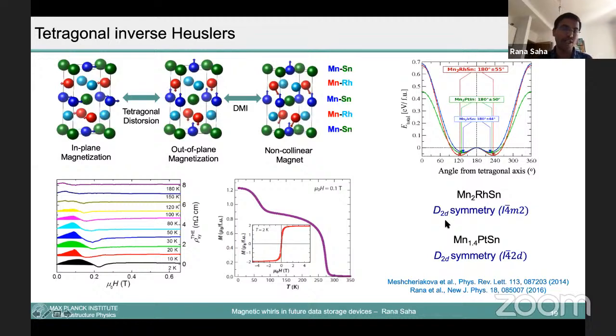In this symmetry, you can stabilize some kind of anisotropy, and also you can have some kind of chiral magnetic interaction. So you can see here, these are the spins. We use this kind of interaction where the spins are aligned along the c axis of the tetragonal structure, where this manganese moment has two types of manganese. One is in the plane of the tin, another in the plane of rhodium, the heavy metal, and the spins are canted. So because of this special kind of magnetic arrangement, it holds the promise of hosting this skyrmion structure, this non-collinear chiral spin structure.